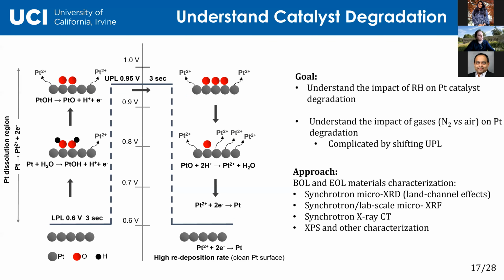So now, for the last 15 minutes or so, I will talk about what we do in our group in terms of durability. This is a cycling accelerated stress test that the Department of Energy developed for fuel cells. You cycle from 0.6 volts to 0.95 volts. What happens in this window is the platinum surface gets oxidized. First you build platinum OH on the surface, and then platinum oxide, and then you reduce this platinum oxide, so platinum ions leave the surface, and essentially that's where degradation happens. When you do this cathodic sweep from 0.95 volts to 0.6 volts, that's where you lose a lot of platinum.